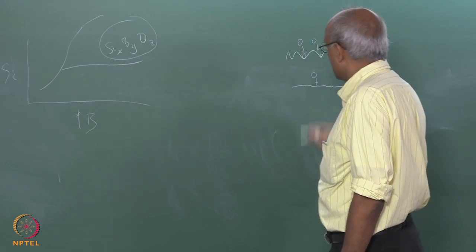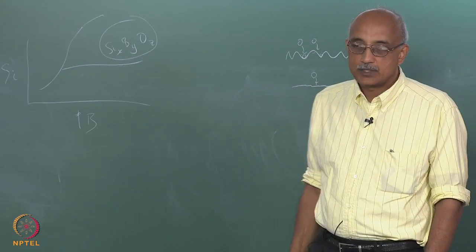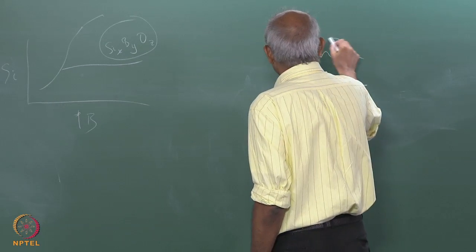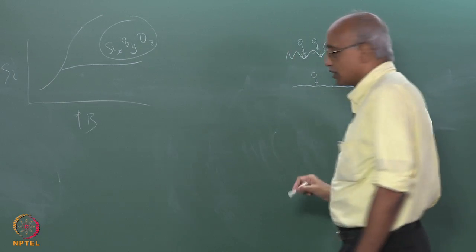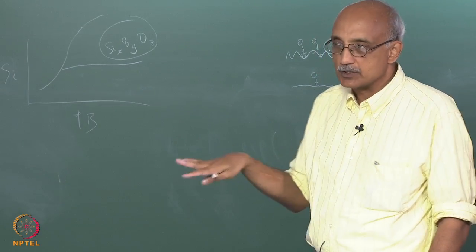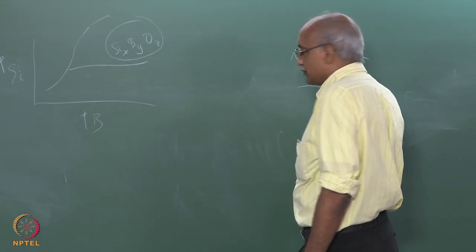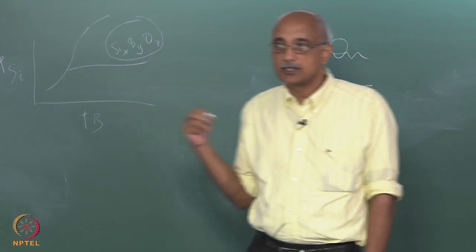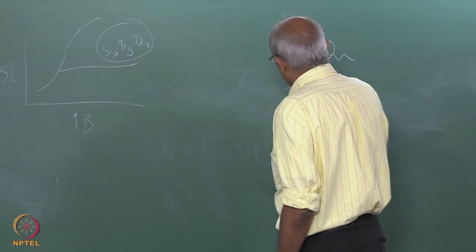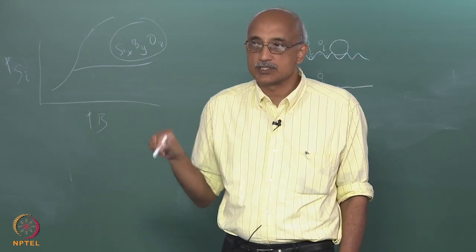On the other hand, if the arriving molecule is larger than the surface roughness, then as you can imagine, its contact is actually going to be reduced. It's going to be now sitting on just two points instead of sitting on the entire surface. So the implication is, as you make the surface smoother and smoother by adding dopants, the probability of capturing an arriving molecule actually decreases.